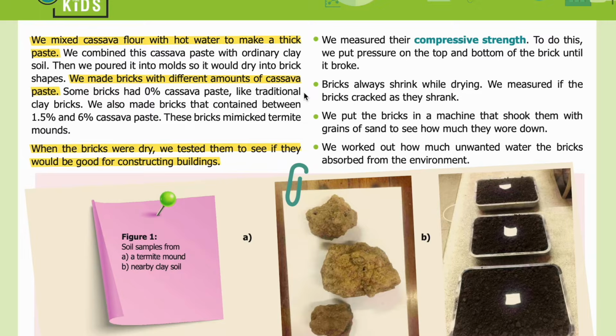Some bricks had 0% cassava paste, like traditional clay bricks. We also made bricks that contained between 1.5% and 6% cassava paste. These bricks mimic termite mounds. When the bricks were dry, we tested them to see if they would be good for constructing buildings. We measured their compressive strength. To do this, we put pressure on the top and bottom of the brick until it broke.